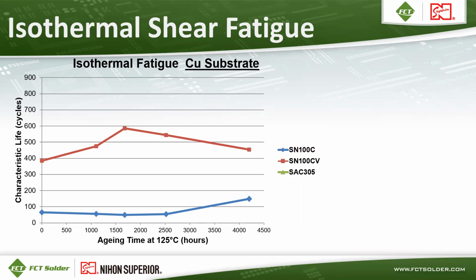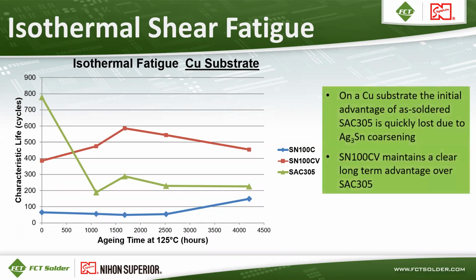SN100CV is the red squares, and that has a much higher characteristic life than SN100C, and it is also stable over the duration of this test. SAC305 starts out initially with the highest characteristic life, but it drops dramatically and becomes fairly low throughout the duration of that test. So the initial advantage of SAC305 is quickly lost due to the coarsening of those Ag3Sn particles, whereas SN100CV maintains a very stable, clear advantage of characteristic life over SAC305 in this test.